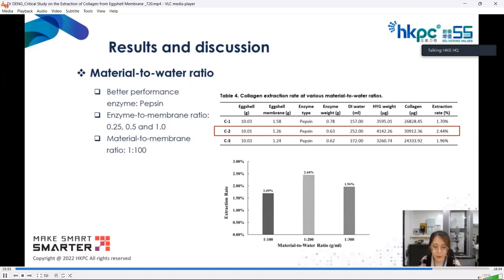The reason for this phenomenon is that the hydrolysis reaction in the high concentration system is incomplete, and the higher concentration collagen hinders the extraction process. Both the degree of hydrolysis reaction and the collagen extraction rate increase with the decrease of concentration. However, the membrane and enzyme concentrations are diluted with adding excess water, further resulting in a decrease in the collagen extraction. Therefore, the material to water ratio of 1 to 200 is favorable in the collagen extraction process.